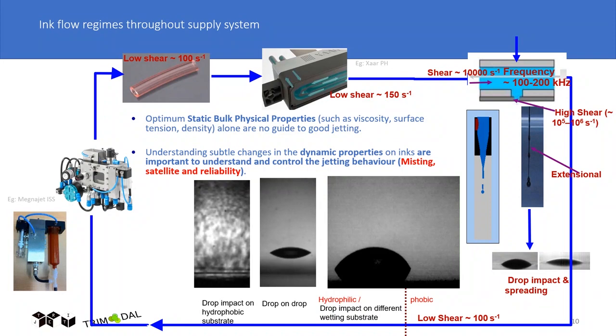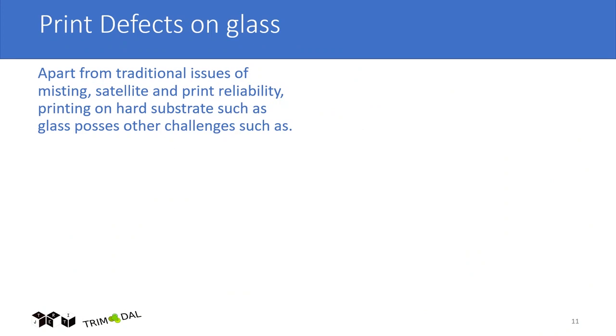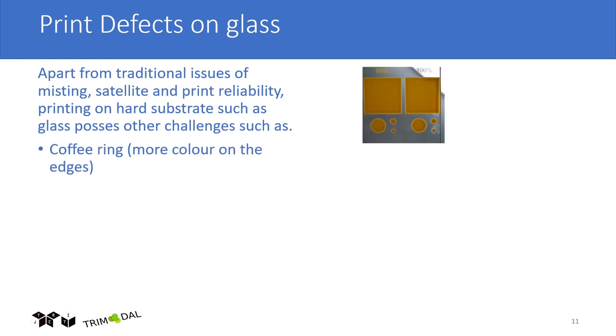But then how do you quantify it? If you cannot quantify it, you don't do it. And then the substrate is very difficult. One of the biggest issues we have printing on glass is the definition issue. So here's again a case of drying. Classic coffee ring effect, right? When you start drying it, the particles migrate towards the edges. So you have a color gradient.